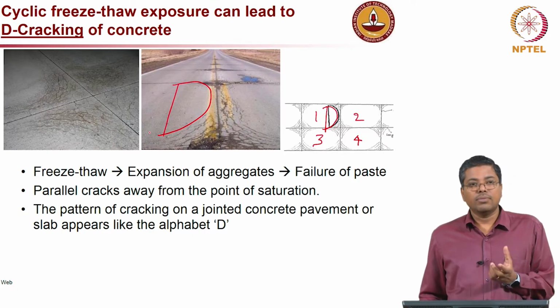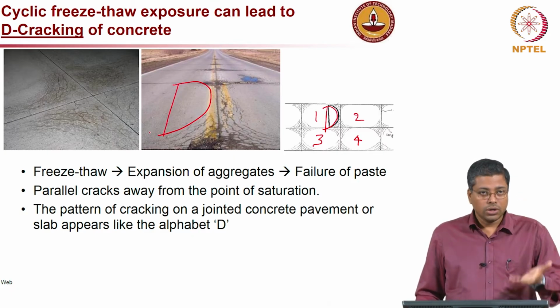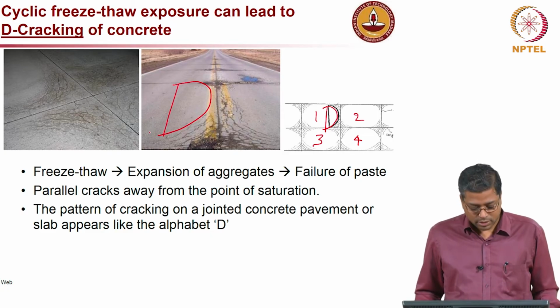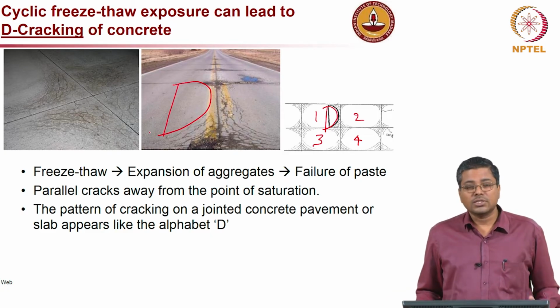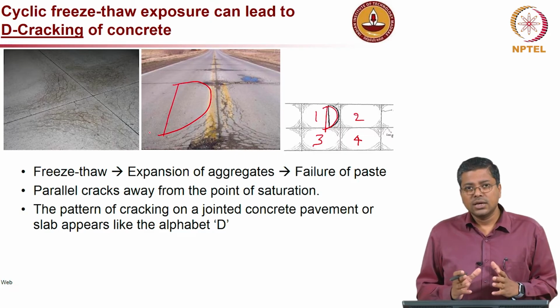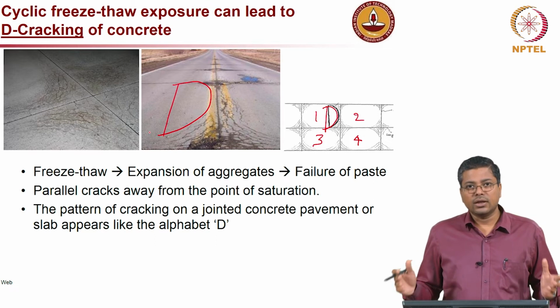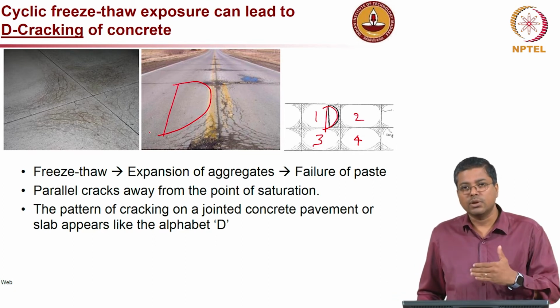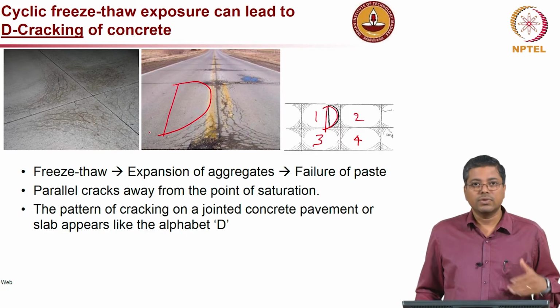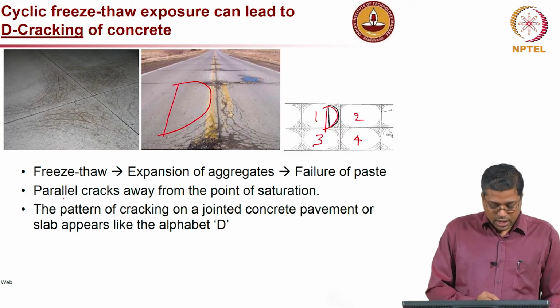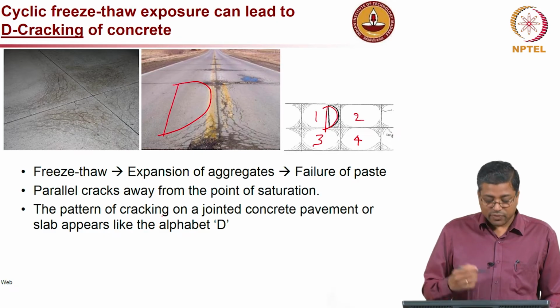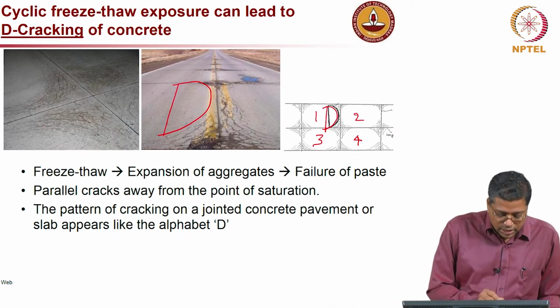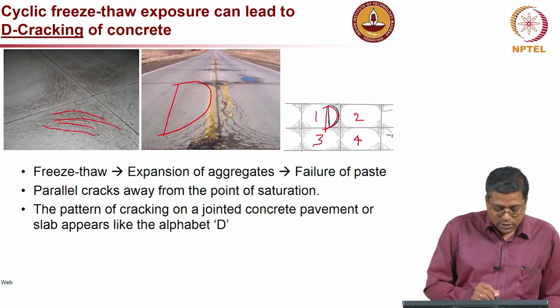And so, what happens during freeze-thaw exposure is that the aggregate might expand, because if there are pores inside the aggregates, they might expand because of the ice formation inside. Eventually those expansive forces will push the paste around, which will lead to the failure of the paste. And then parallel cracks away from the saturation points. So, you can see these cracks, these are the parallel cracks which are actually happening.